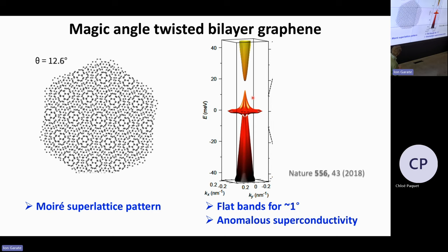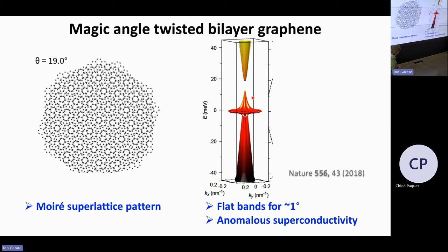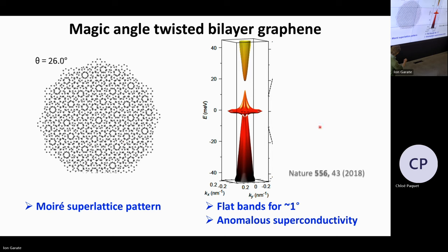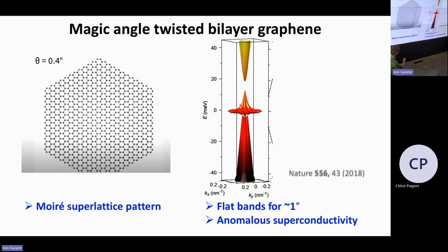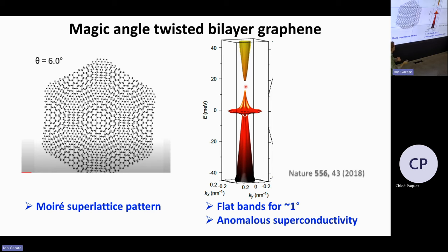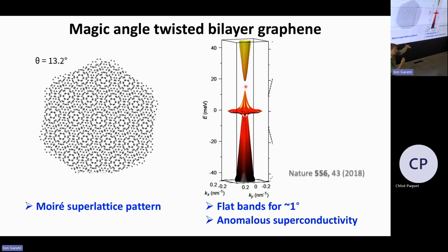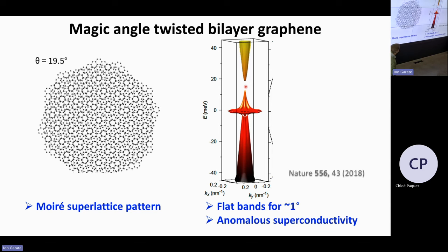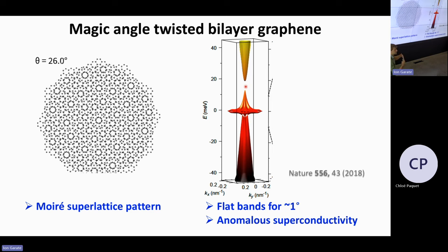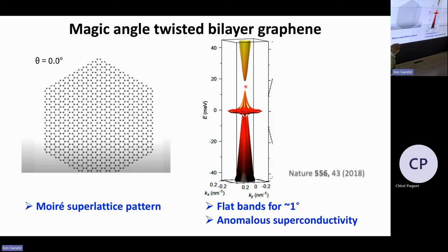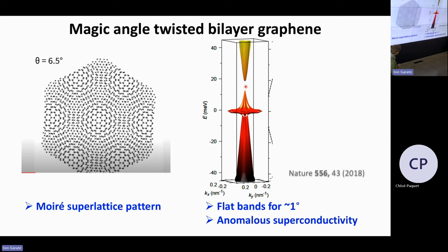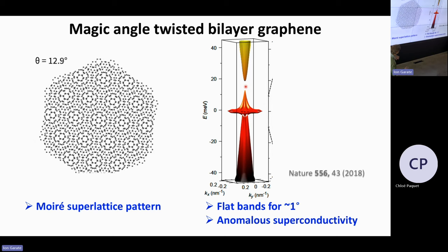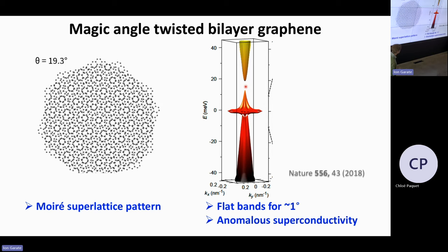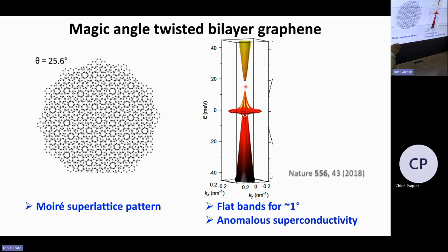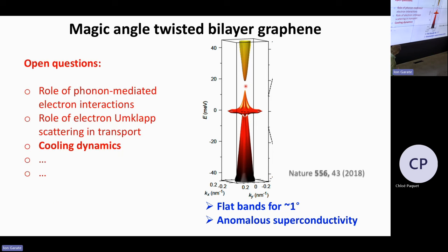And then what's really interesting is that at certain angles, around 1 degree, you actually get the formation of flat bands. Of course, graphene is known for its Dirac cones, but in this case you have a small band gap and flat bands within this band gap. And these flat bands, of course, give rise to strongly correlated effects. And in this case, even the demonstration of unconventional superconductivity below 1 Kelvin. So there are some very interesting things going on, with lots of open questions still.